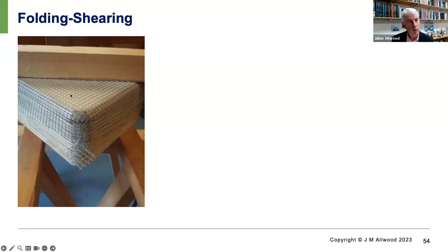And instinctively, we folded over the edges, leaving us with a cone at the corner. And then we used our thumbs to press the cone down, incrementally moving towards the outside. And we found, and you can see here, that there's a square of material that's been sheared out of the sheet. But the diamonds in the middle there show that the sheet largely deformed in pure shear, which is perfect for sheet forming because it means the thickness doesn't change.